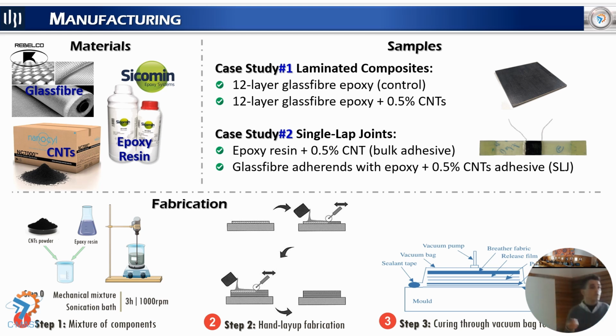For the manufacturing of the samples to perform the study, we used glass fiber as the fiber reinforcement, carbon nanotubes as the nano-reinforcement, and the polymer matrix was a conventional epoxy resin. For the first case study, the laminated composites, we produced layered glass fiber composites, two sets of samples. The first one, 12-layer composites of glass fiber epoxy, so pure epoxy with glass fiber reinforcement. This is the control sample. And for the samples in which we studied the piezoresistive effect, we had the epoxy resin with 0.5% by weight of carbon nanotubes.